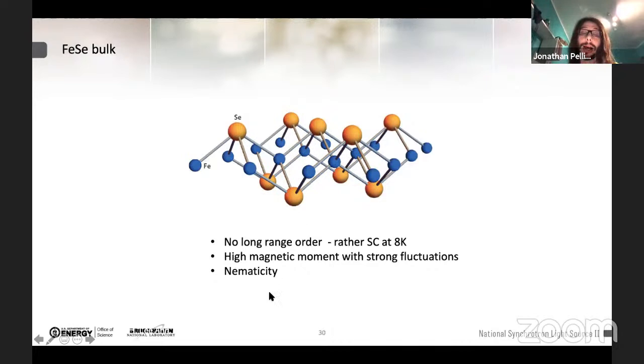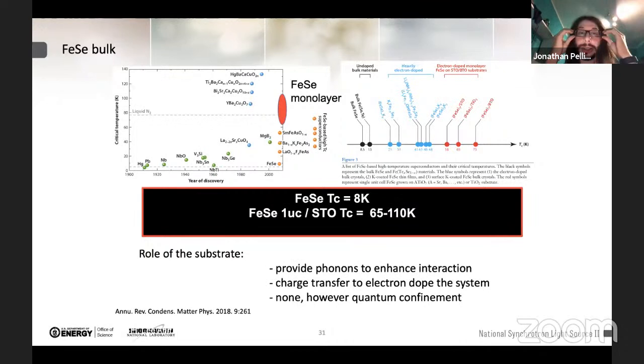But what is even more interesting is that when you grow iron selenide on a substrate and you limit the thickness to one unit cell, the superconducting temperature is boosted by almost an order of magnitude. And if we were to place in this diagram, where we plot the Tc versus the year of discovery, the iron selenide monolayer, we would see that it has a pretty strong position compared to all the other iron-based superconductors. And it is the one that presents the highest temperature.